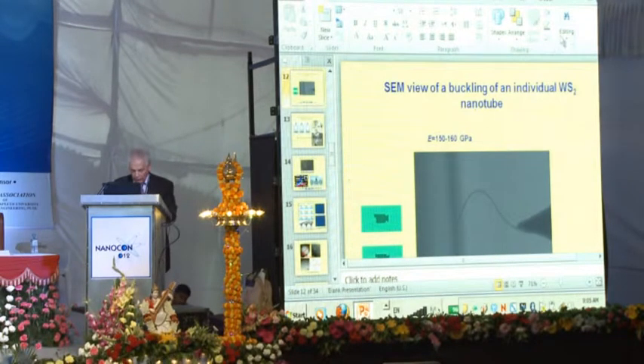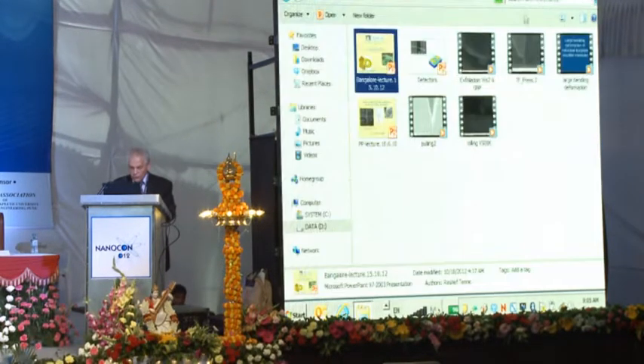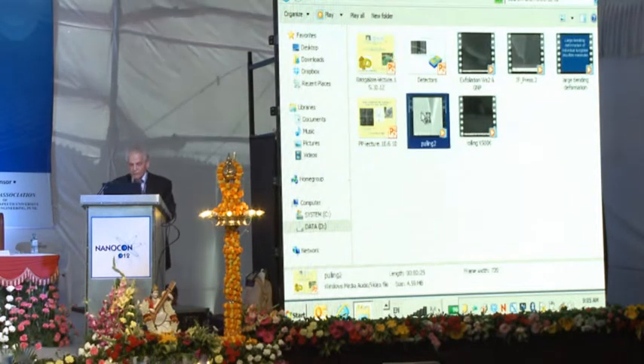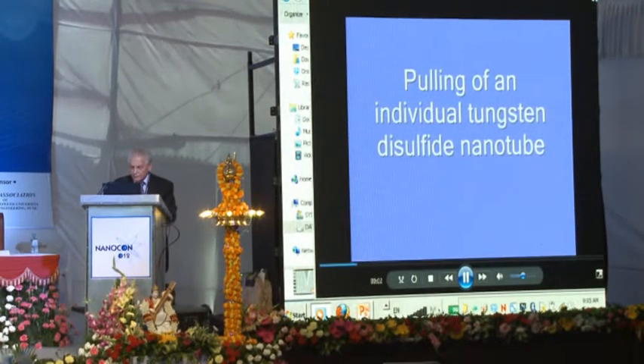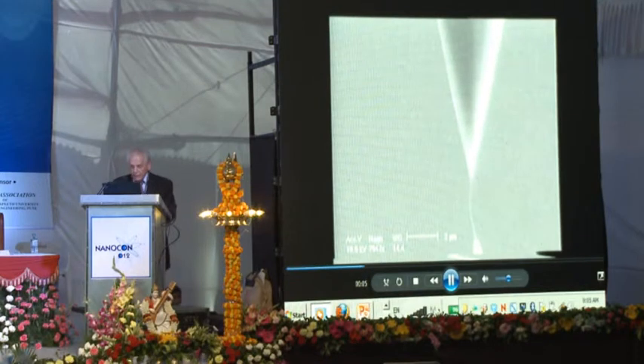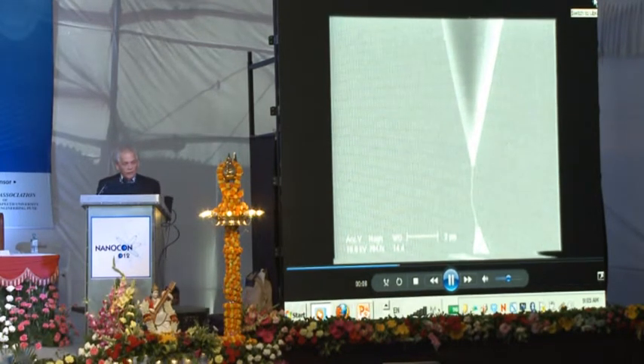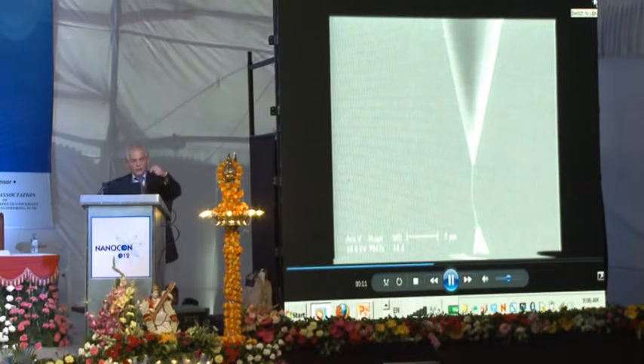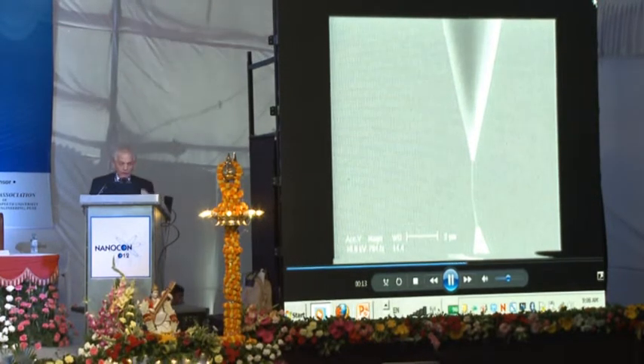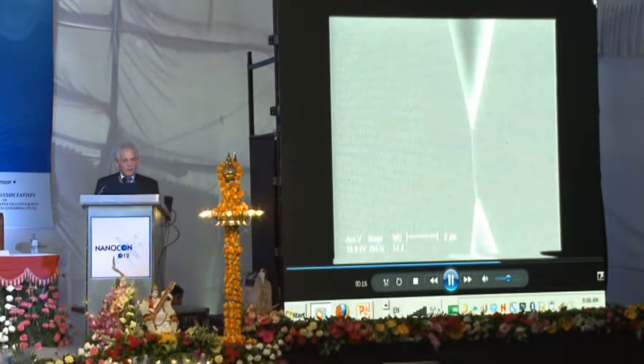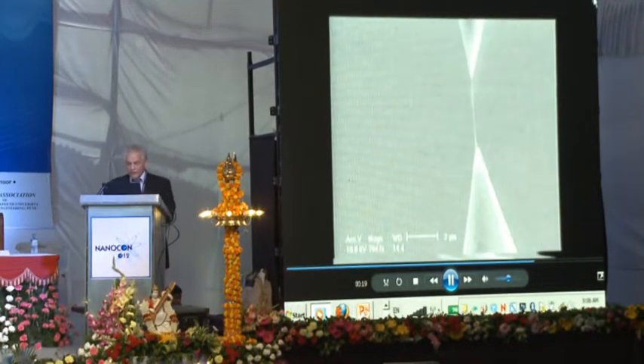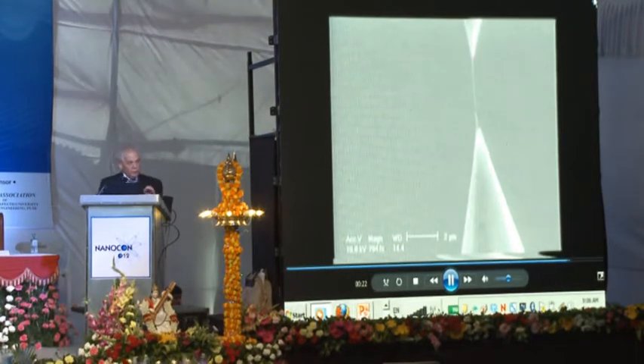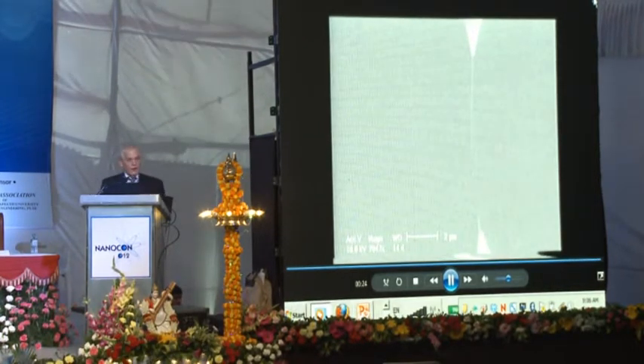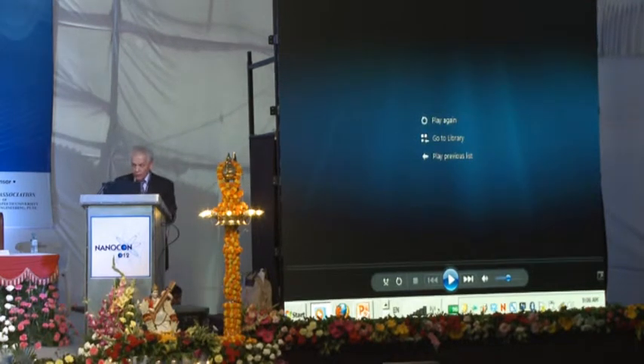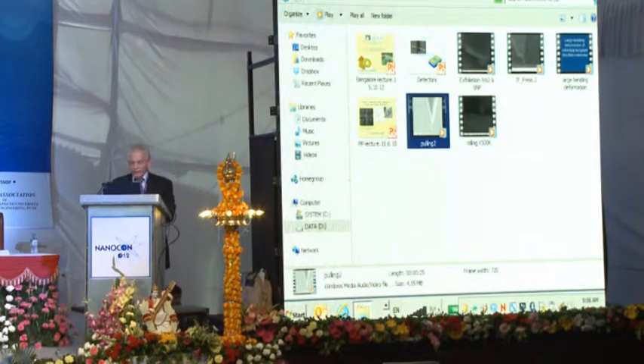I'll show only 1 or 2 of those movies. So these are 2 movies that were produced. First, I'll show this movie. This is a movie that shows the tensile experiment of one single nanotube glued to 2 AFM tips. And this experiment was performed by Yifat Kaplan-Ashiri. It is a completely quantitative experiment. It's not just a nice picture. So you really have to exert a lot of force in order to break these nanotubes.